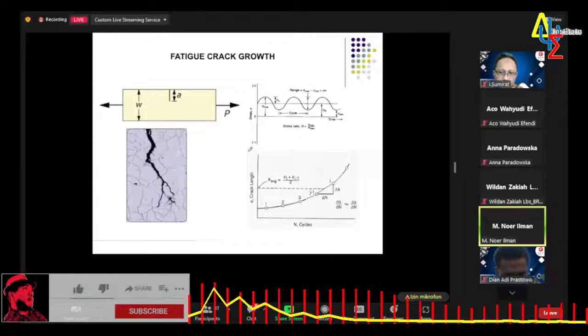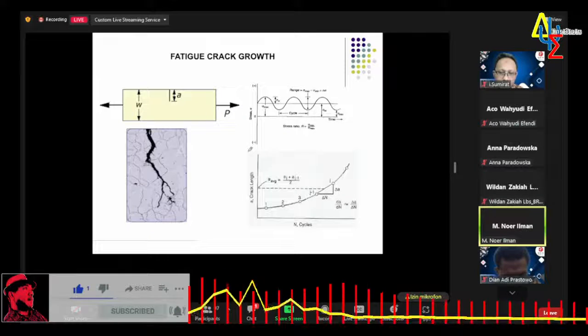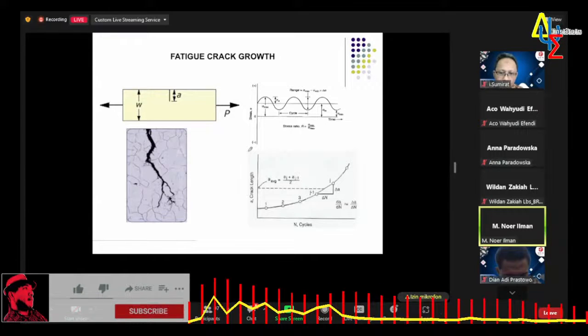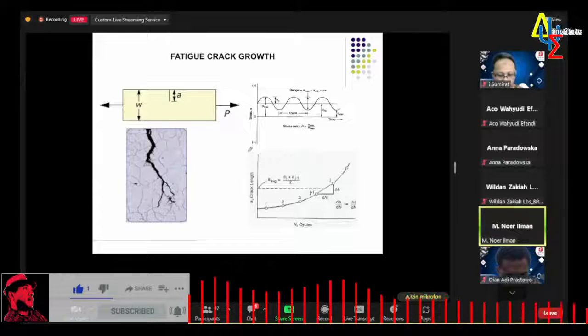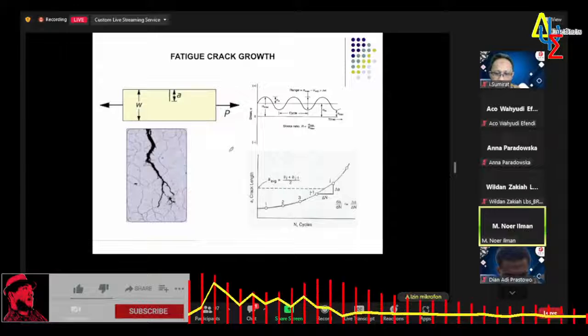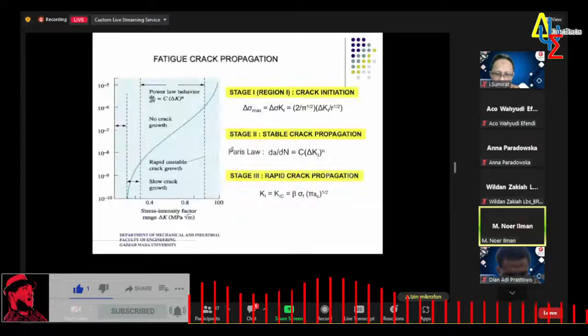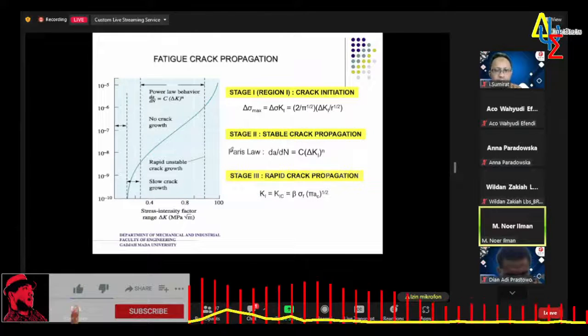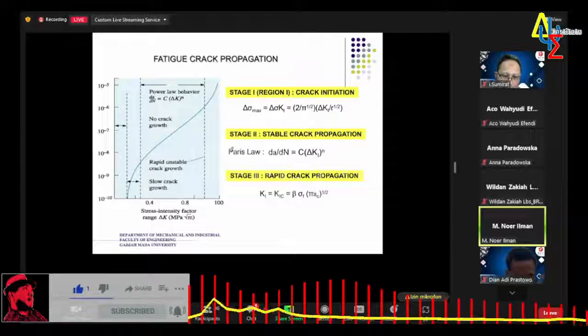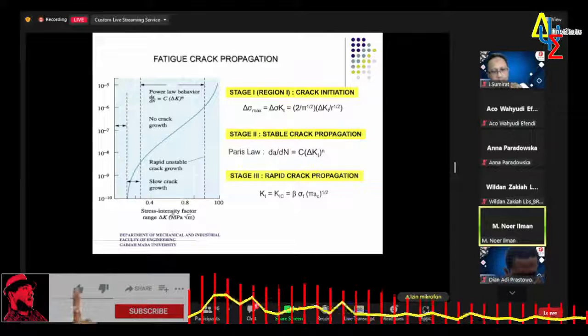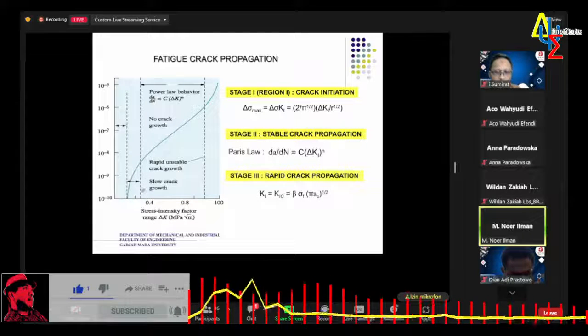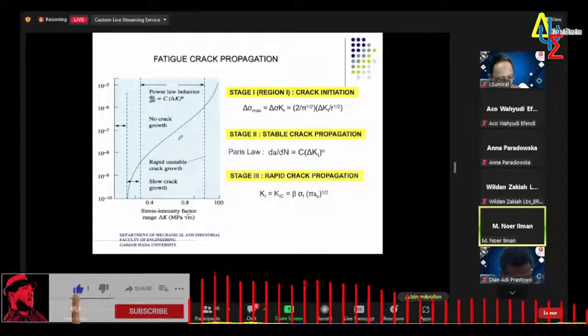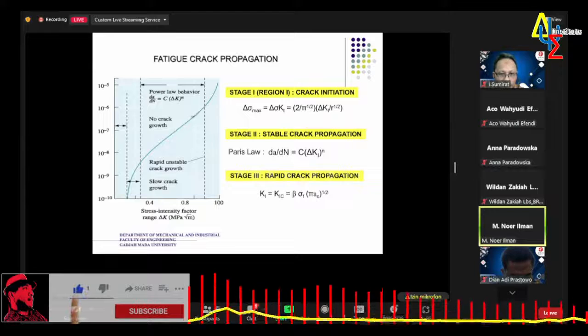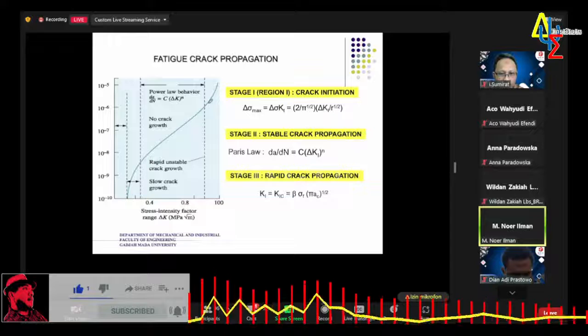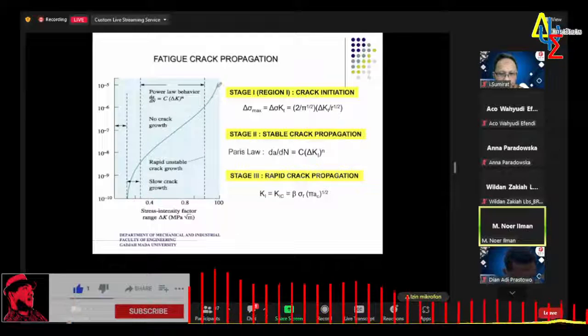And I think this is an example of an experiment to study how the crack grows under dynamic loads. And this is the main focus of our research. And normally, the fatigue crack growth rate behavior of a material can be studied using this da/dN as a function of stress intensity factor range, delta K. And from this diagram, we can see three different regions, which are crack initiation here, and then stable crack growth, which follows Paris law, and then the final fracture here in stage 3.